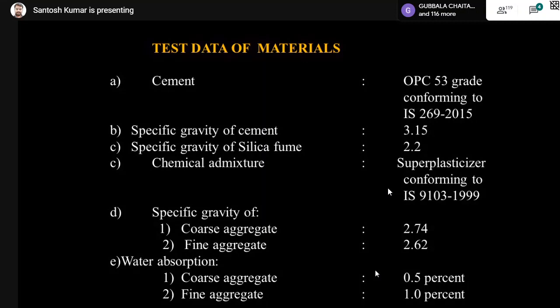Chemical admixture conforming to IS 9103. Specific gravity of coarse aggregate is taken as 2.74 in this design, and fine aggregate specific gravity is taken as 2.62. Coarse aggregate water absorption is taken as 0.5%, and fine aggregate water absorption is taken as 1%. But one thing I want to tell you here, the 1% fine aggregate water absorption in the standard which has been referred to in the example is only for river sand.